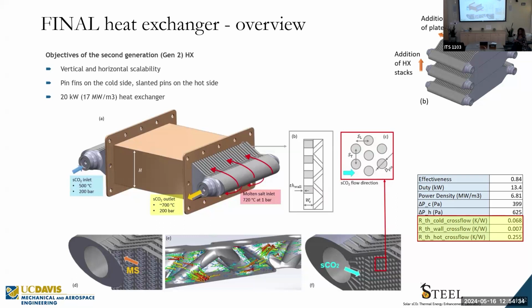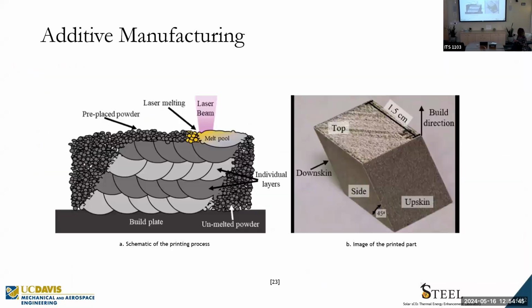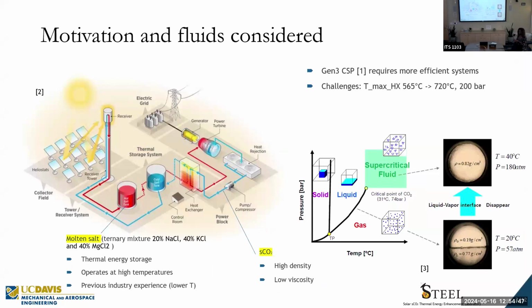Is there a reason behind choosing this chloride salt versus some other? Nitrate salts are what was used in the first generation of solar thermal with storage, back to Solar Two in the 90s, which is basically a sodium and potassium nitrate mixture. It degrades or decomposes at around 580 to 595 degrees Celsius. If you want to go any higher, if you want to go to 720 for CO2, you need a salt that goes even higher. So this ternary mixture of chloride salts is one option, but it's highly corrosive.